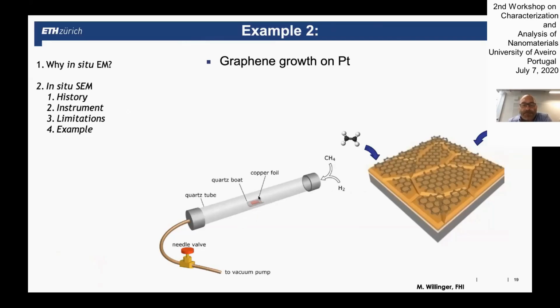You don't see much, this is very hot and shines bright, so you grow, and after growth you study what comes out. And we did this in the microscope. We heated copper, platinum, nickel, different metals in the microscope to 1000 degrees, and introduced hydrocarbon and hydrogen. And we really could see at 1000 degrees the formation of graphene, which, as you know, is a monolayer of carbon.